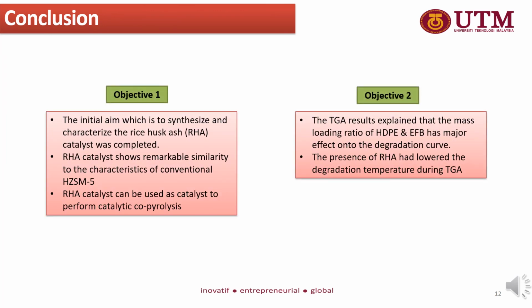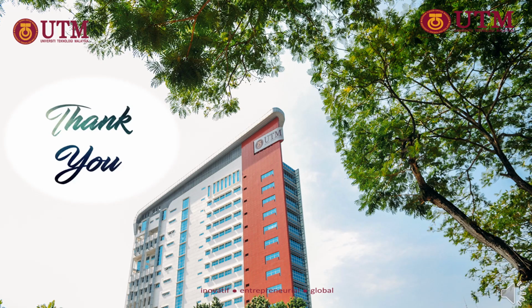To conclude the experiment, both objectives have been achieved as the RHA catalyst was synthesized and characterized. Next, the investigation of the mass loading ratio also showed that the mass loading ratio of HDPE and EFB affected the degradation curve, and the presence of the RHA catalyst lowered the degradation temperature during TGA. We've reached the end of the presentation.